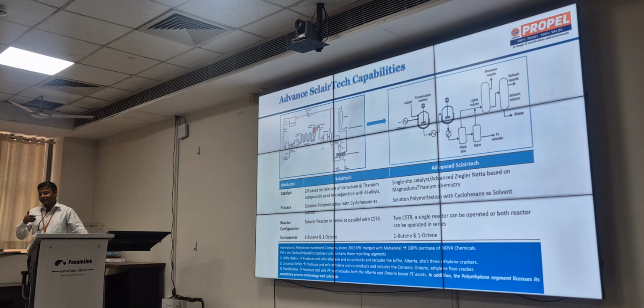That's why no domestic manufacturer wants to come with bigger lines in the metallocene. But if we can take smaller lines like 150 or 200 KTA, where we can take regular runs of 10 days and 15 days. So this is the challenge to run metallocene based grades to produce on the same lines.